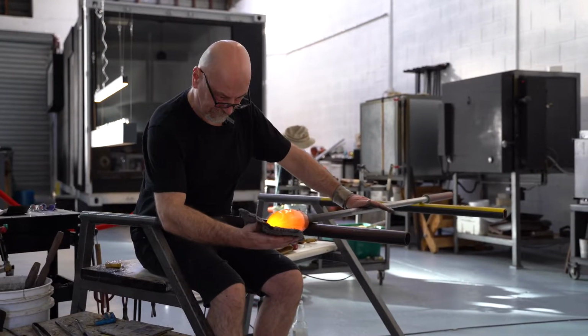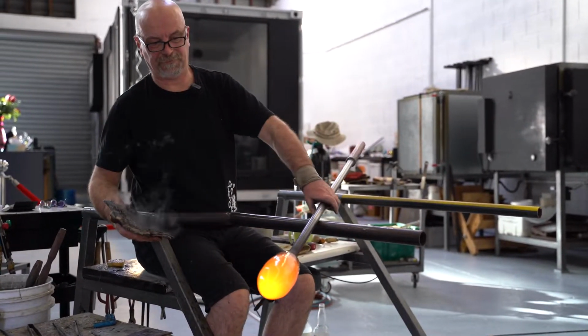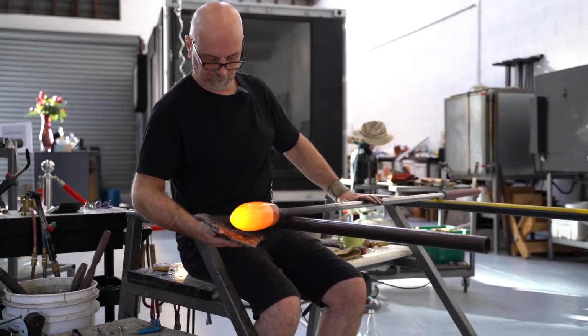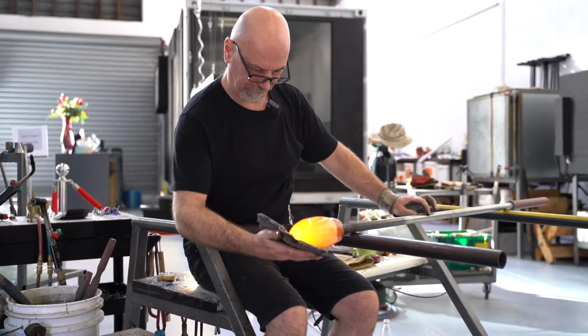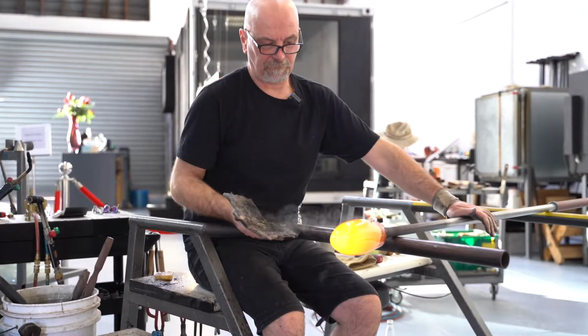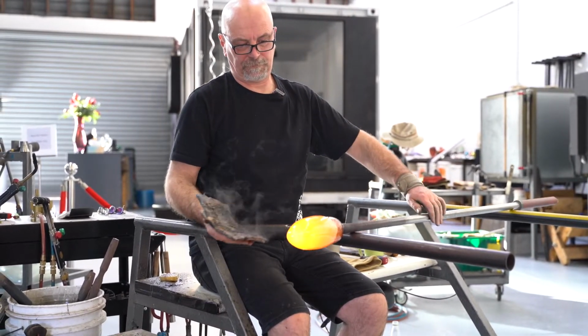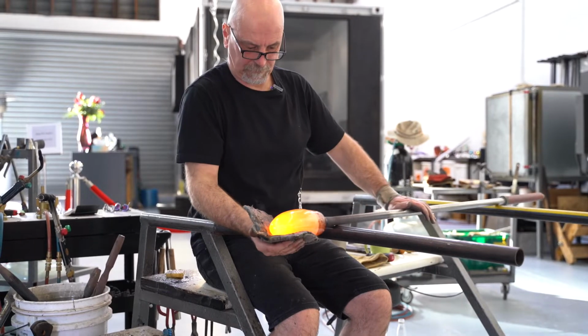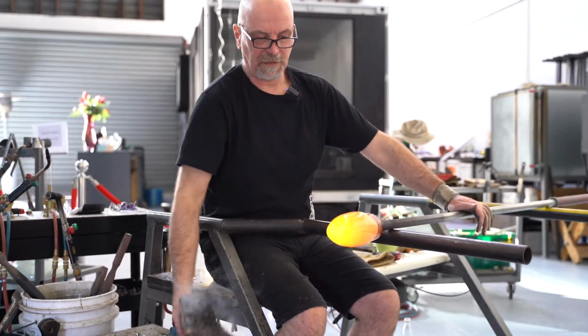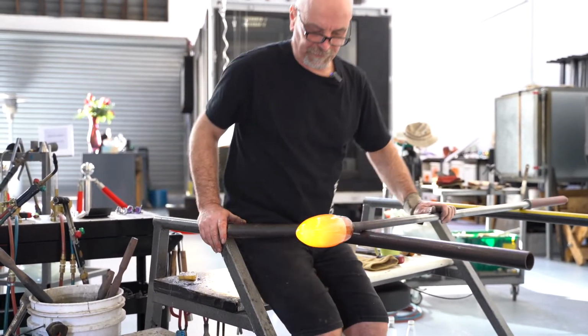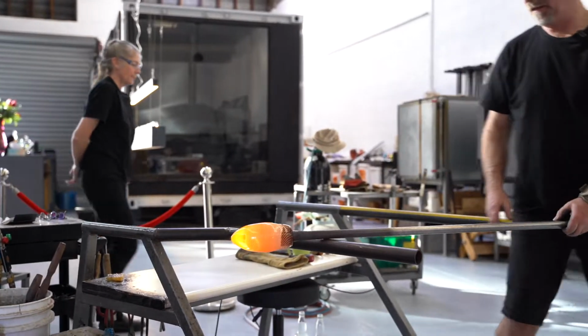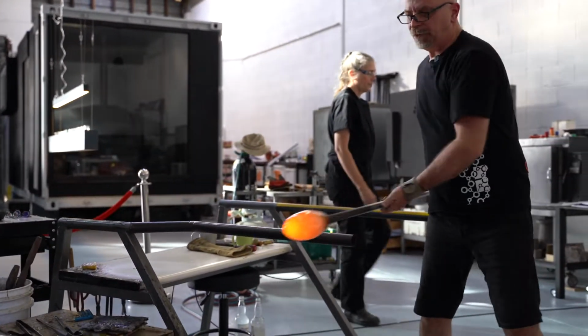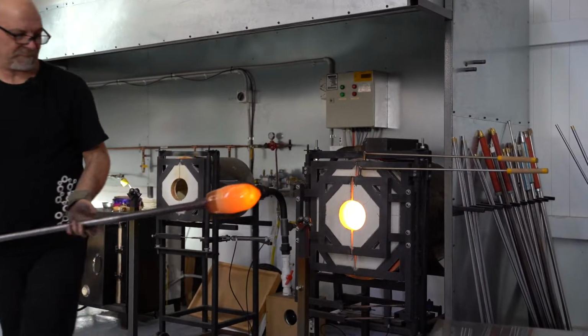So using wet newspaper as a shaping tool here, what actually happens is the heat of the glass is driving the moisture within that pad to steam, and then the glass basically just rides on a bed of steam. So there's not so much contact actually with the paper. The glass is riding on a bed of steam. Right.